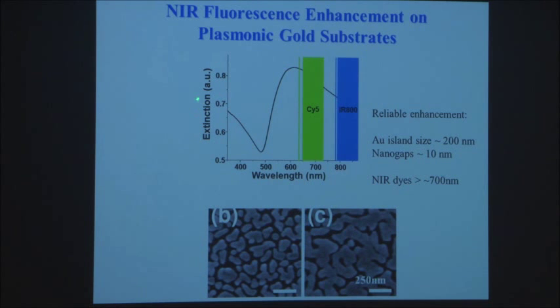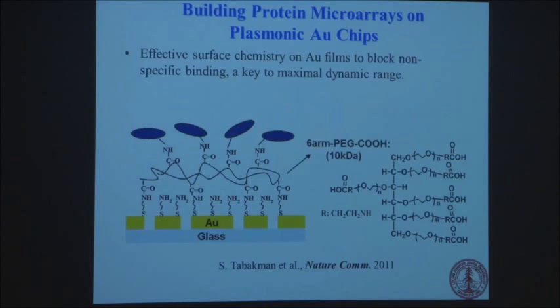So this is the absorbance of these two films, and you see there's this peak here. That's the plasmonic excitation in the film. When the absorbance matches the emission of the fluorophore, that's when the fluorescence is enhanced the most. So once you reach these requirements, you can get up to 100 times fluorescence enhancement, which you can now use to do protein detection.